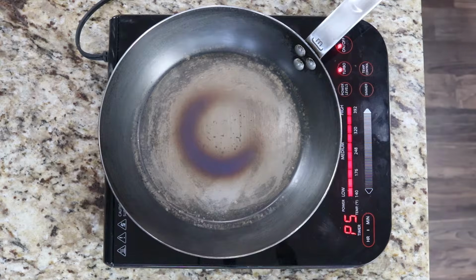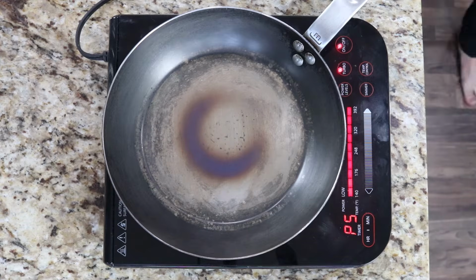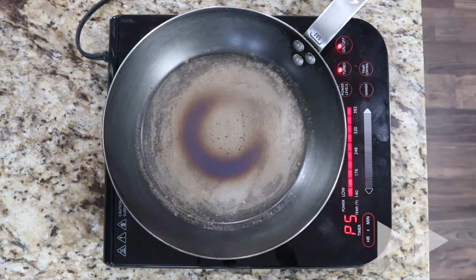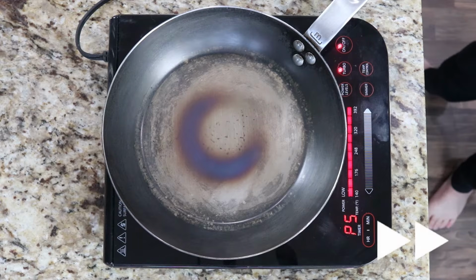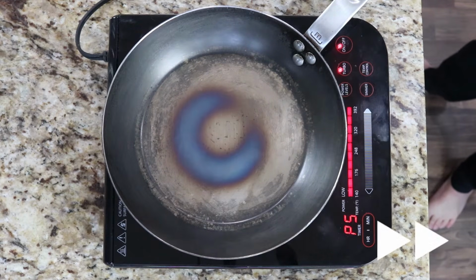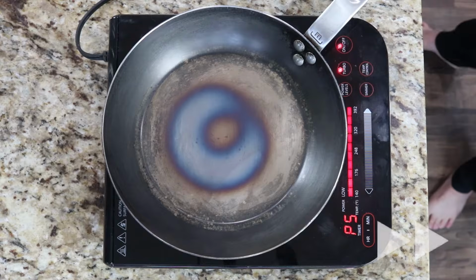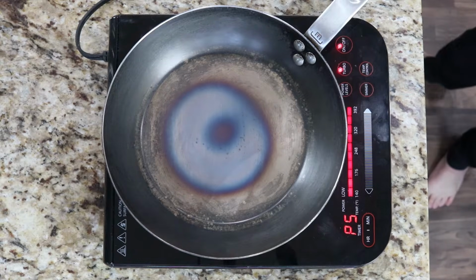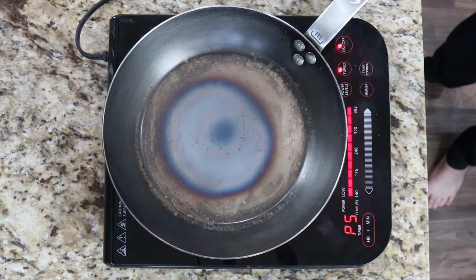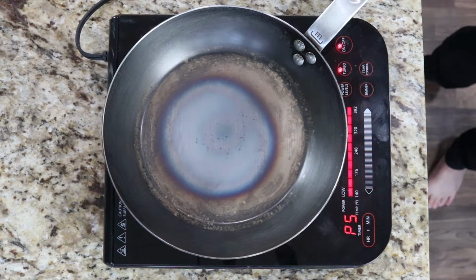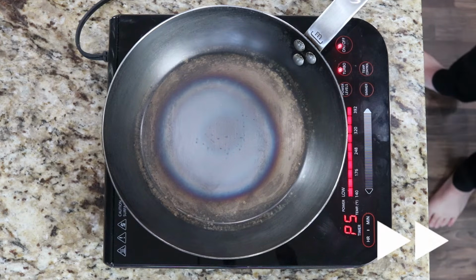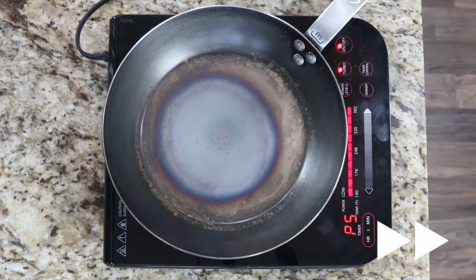Dry off the pan completely and put the pan over your stovetop over low-medium heat. In this first step, we're going to oxidize the bare metal surface, also known as bluing the carbon steel. This process creates a layer of black iron oxide on the metal surface, and the black iron oxide finish will give the steel a beautiful black, blue, aqua appearance. And the surface adheres well with oils and gives your carbon steel one more layer of rust resistance.